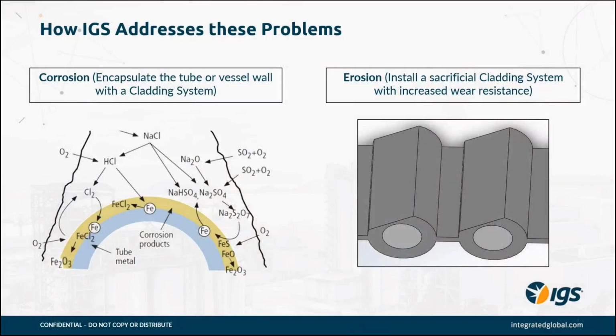So at a high level, what is IGS doing with these cladding systems? If we think about corrosion, IGS is encapsulating the boiler tube with a cladding material that's non-reactive to the gaseous constituents in the combustion atmosphere that were previously interacting with the carbon steel tube surface. In an erosion sense, we're again encapsulating the tube, and the important part is with a material that is significantly more erosion resistant than the base tube material. So, implementing a sacrificial barrier that is significantly more erosion resistant, to the tune of 8 to 10 times more erosion resistant than the base tube material.